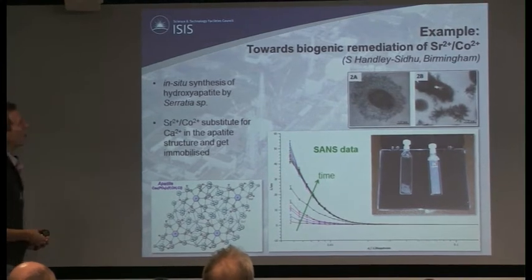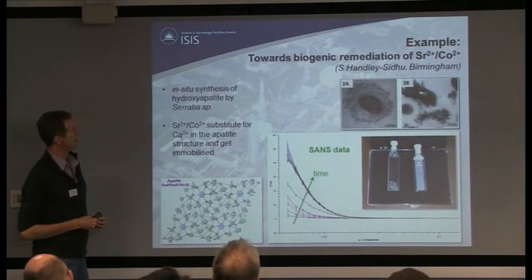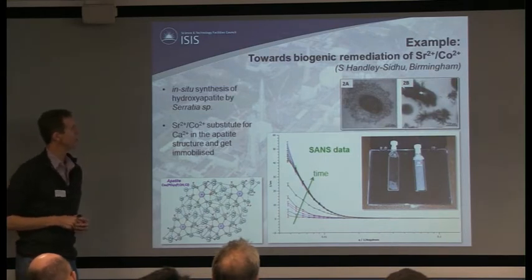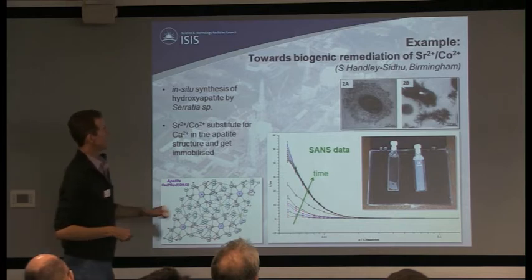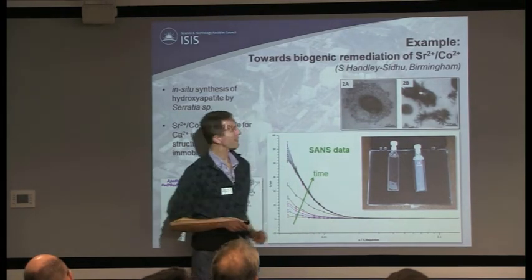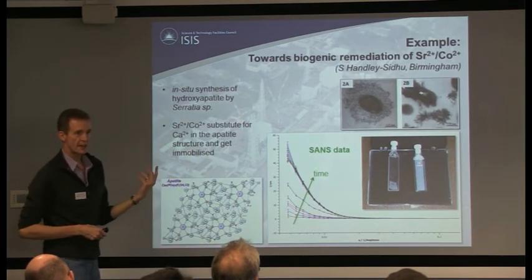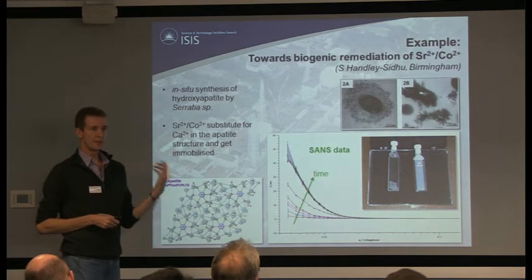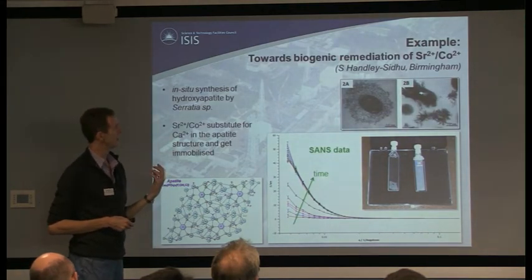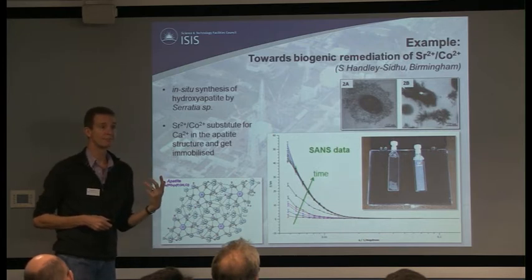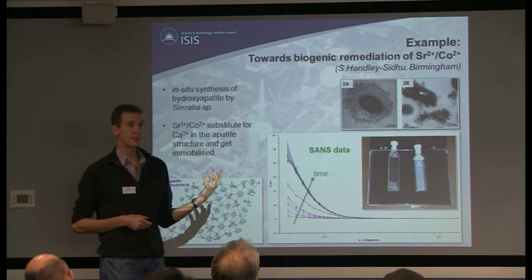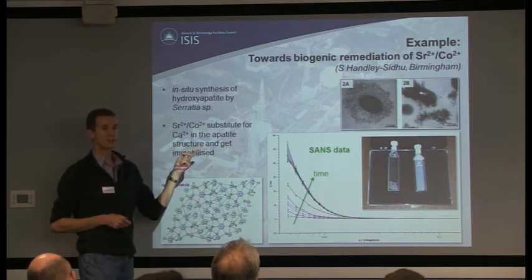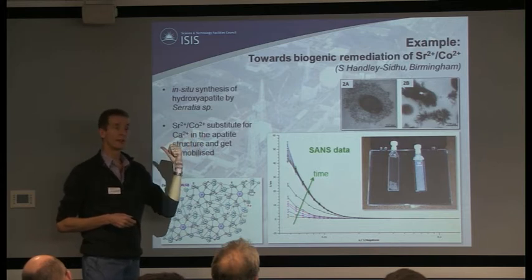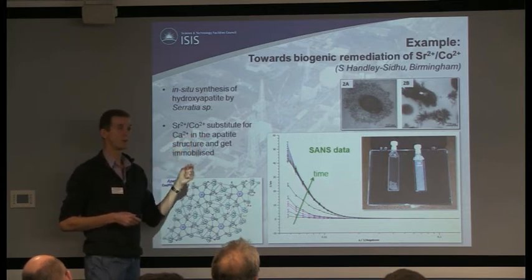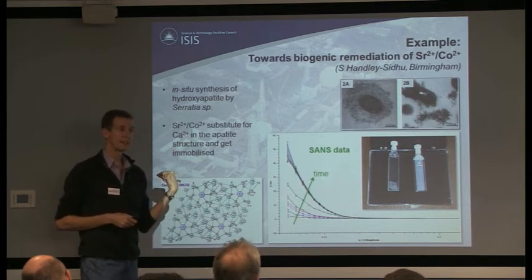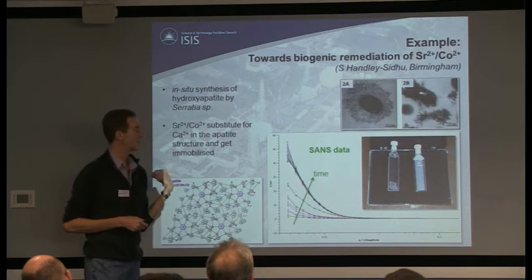One very quick example was some work we haven't quite finished writing up yet, from Stephanie Handley-Sidhu at Birmingham. This is a bacteria that has a phosphatase enzyme in its outer cell wall, and if you feed it the right sort of cations, it will produce phosphate. So if you feed it calcium, it will produce apatite, hydroxyapatite. On the other hand, if you feed it strontium or cobalt, it will form apatite with the strontium and cobalt sitting on the atomic positions that the calcium would normally take.